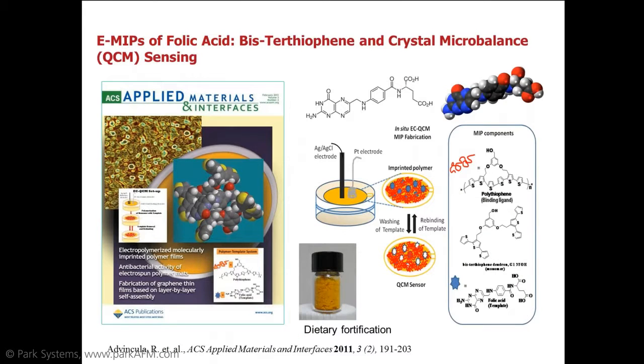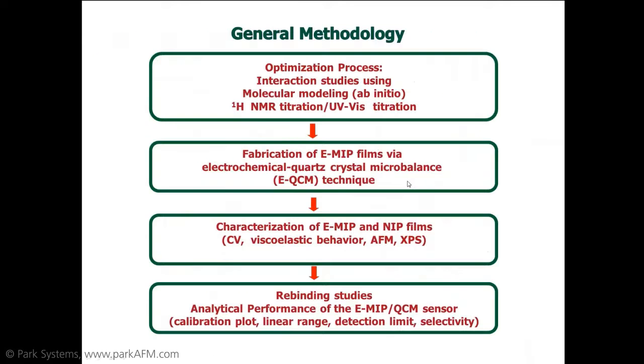Now going forward, just showing you that molecular imprinting is not an aberration, and that it works very well, is that we can molecularly imprint virtually any chemical of our choosing. In this case, we demonstrated with folic acid. Folic acid here can be electropolymerized together with the bifunctional monomer on a quartz crystal microbalance surface, and we can detect the molecule. Okay, this is just a general methodology of the process.